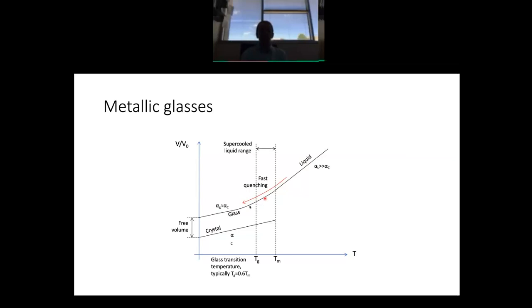Most of the time when people make these kinds of glassy materials, they'll use a multiple component mixture, right? So for example, copper zirconium is a 2-component metal which can be made glassy by quenching at very high rates. Okay, and people have figured out how to adjust the compositions and adjust the quench rates to actually make fairly substantial amounts of these amorphous metallic materials, or bulk metallic glasses, if you will. So this is an example of a bulk metallic glass specimen. These are sort of centimeter scale specimens of bulk metallic glass.